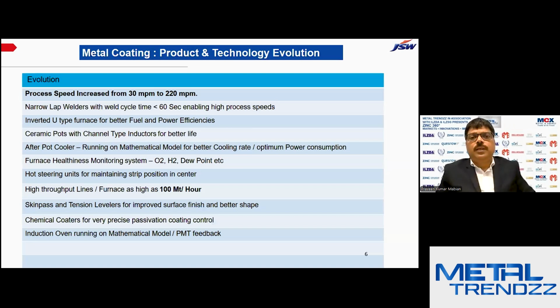So what exactly did we do in order to have this growth? There are so many product and technology innovations and evolutions done in the process. Starting from 30 mpm speed, we now hold the metal coating line which is operating at 220 meters per minute speed, which is the fastest in India. So we have done a lot of innovations. We have made investments on the technology part.